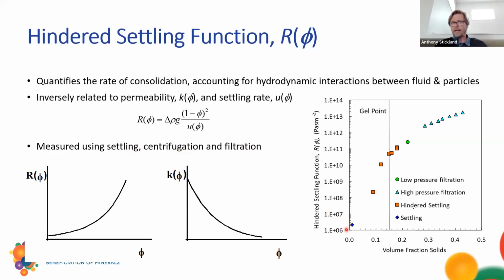And here's some results for, I think, zirconia off the top of my head. I think it might be a fine zirconia suspension. You'll see here free settling behavior 2 by 10 to the power of 6. And as we increase the concentration, that drag parameter increases by 7 orders of magnitude. So by the time we get to a filter press and we've got it in there at 40 volume percent, our drag has changed very dramatically. Very few engineering parameters change by that many orders of magnitude in the same device. In order to measure the drag across all of those concentrations, we use a range of different techniques, but we can get sedimentation rate behavior around about the gel point, and then filtration behavior at a high concentration.